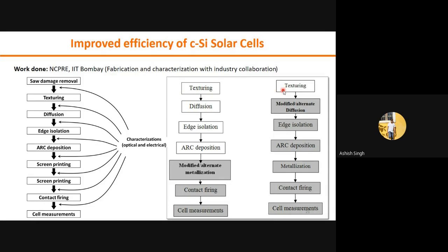So these were the two sequences we were following. In this sequence, the gray box activity was ours and the white box activity was industry's. So for example, if we take this one, industry gives texturing, diffusion, edge isolation and ARC. That means they give a half processed solar cell, and we do metallization, contact firing and cell measurement. And in this condition they give just a textured wafer, and we make the complete solar cell out of it. And we were suggesting our input to industry to change their line process for efficiency improvement.